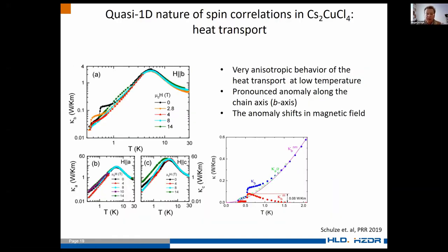We also did heat transfer measurements on this material, and we observed that the heat transfer is most pronounced in one direction, the direction of the quantum spin chains. That is also quite straightforward evidence that this is a one-dimensional spin liquid, not 2D. Otherwise, we would see similar behavior in two different directions in the plane, but we have this enhancement of the heat transport only in one direction, along the chains.